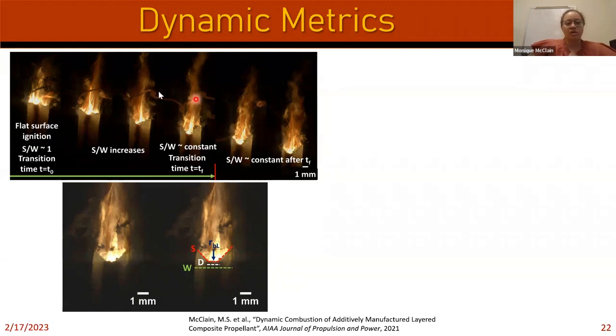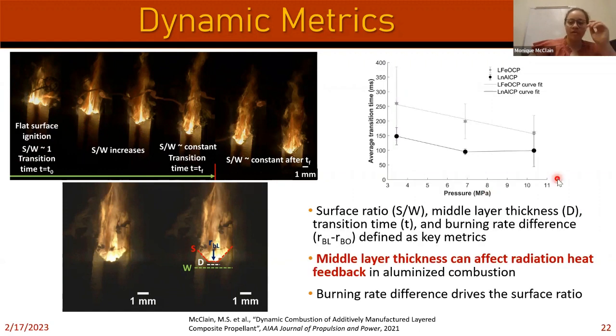It doesn't really look like it's increasing anymore. So we tried to quantify something called transition time: the transition from a flat surface, where S over W is 1, to where it does increase, but then stabilizes again. We quantified that value, and we found that for the nano aluminum, that transition time was relatively fast, or faster compared to the iron oxide. But in general, there are a lot more things to define in terms of this combustion. We're very used to just saying, what's the linear burning rate, and looking at data that way. We're not really used to looking at what happens when you have a multi-material system. So we're definitely looking into understanding those dynamics more.